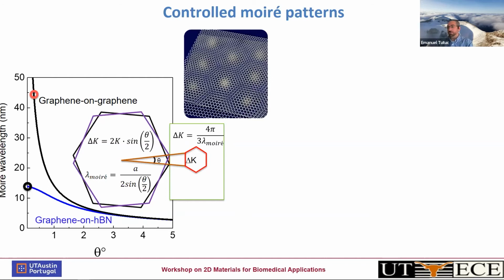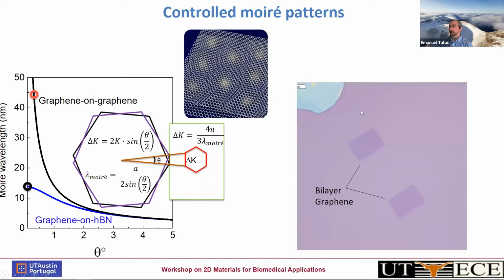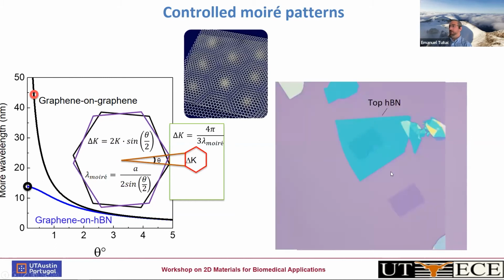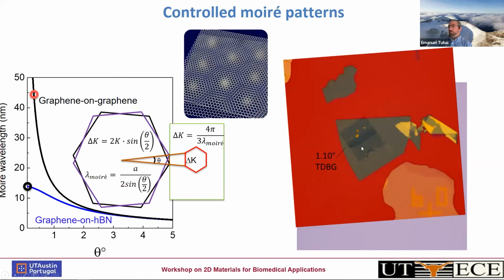So the Brillouin zone is going to become much smaller just because we have a longer wavelength in this heterostructure. How we do this, we would start with two segments. These two layers stem from the same large grain. They've been isolated using, in this case, lithography and etching, but they're rotationally aligned. They stem from the same larger grain. So therefore, the crystal axis of these two segments is in the same direction. We'll pick one up, then twist it slightly and land it on top of the other one. So then in this overlap area, there's going to be a twisted graphene system.